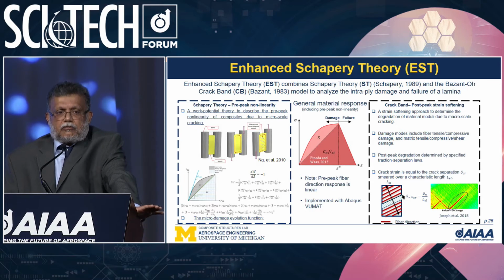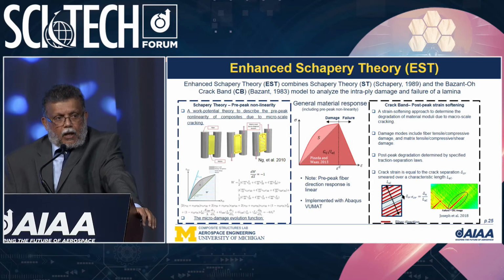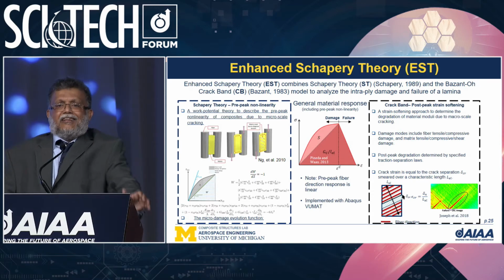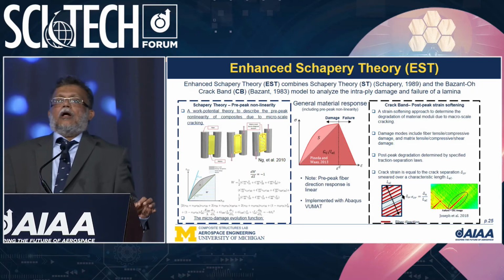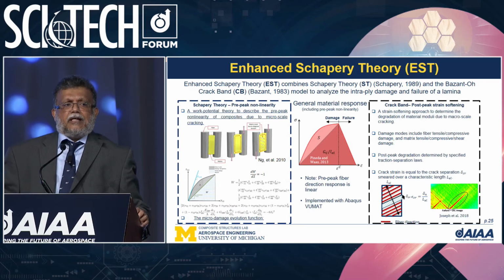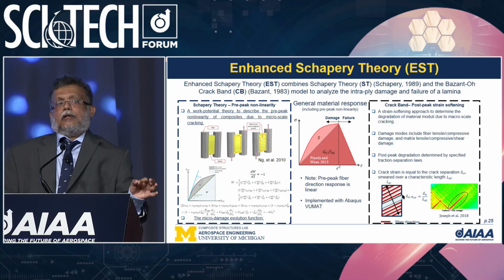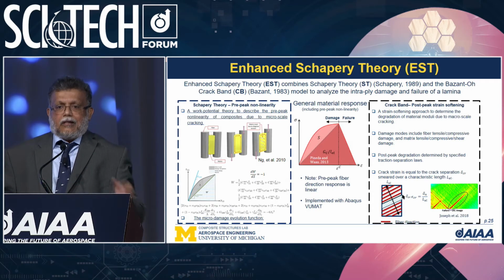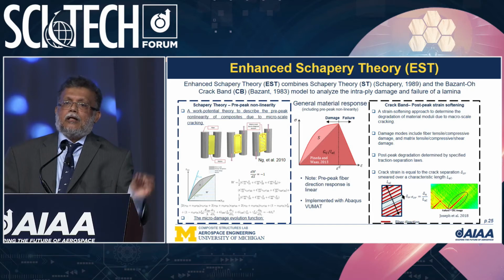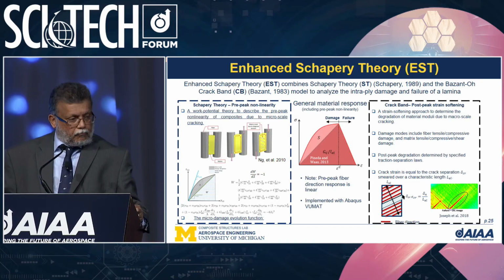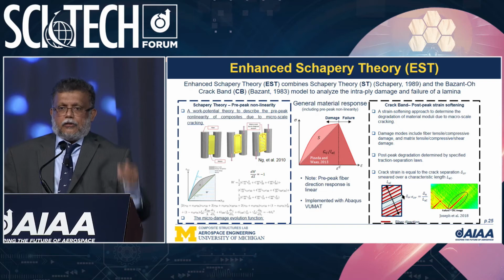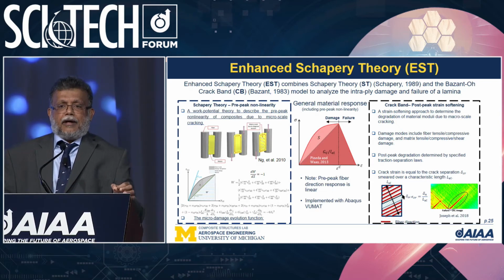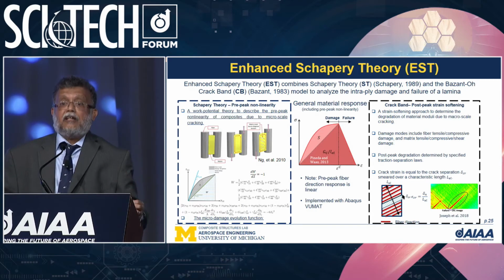Matrix resin materials, when subjected to shear, undergo microcracking. We call that damage because at the length scale of the cracks relative to the laminate scale we are analyzing, those microcracks don't directly affect it—the scales are separated large enough that at the laminate scale, those cracks can be thought of as damage. However, when the damage accumulates, you reach a peak point where you get a macroscopic transverse crack. That's when your stress drops and your strain still increases. That's captured with the crack band method.